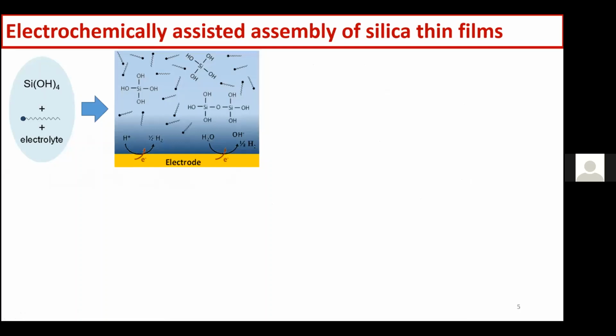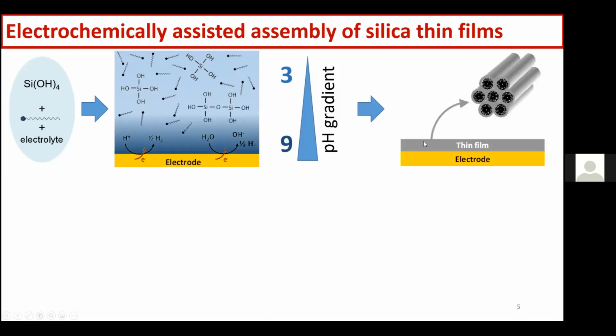a new method to form mesoporous silica thin films was developed in the group. So what we did is we took hydrolyzed silanes that we mixed with cetyltrimethylammonium bromide, the surfactant, and with some electrolyte. We immersed the electrode and applied a reductive potential that was reducing protons and reducing water. And so we were changing the pH in the vicinity of the electrode, and we were getting a pH gradient. Close to the electrode, we had basic conditions, and in the bulk we remained at pH 3, which was the hydrolysis pH. As a consequence, the thin film was growing from the electrode surface towards the bulk.